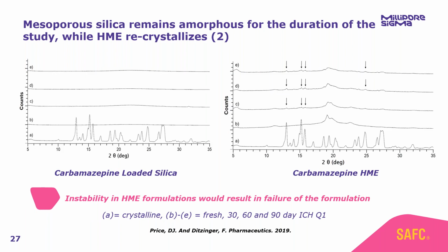The same situation was observed with carbamazepine. On the left-hand side, we have carbamazepine-loaded silica. And again, crystalline carbamazepine on the bottom. And as we go up, fresh, 1 month, 2 month, 3 month, same story as haloperidol. Our carbamazepine at a 20% drug load remained amorphous for the duration of our study, and indeed remains amorphous to this day. For carbamazepine HME, we get the same scenario as for haloperidol.